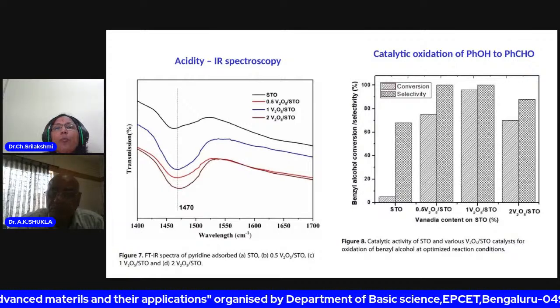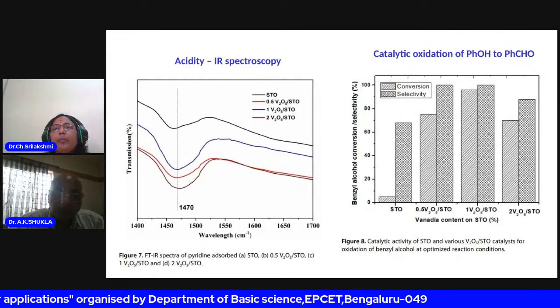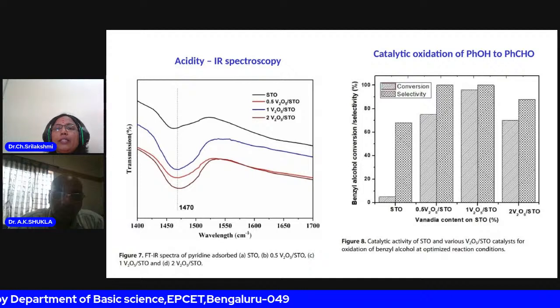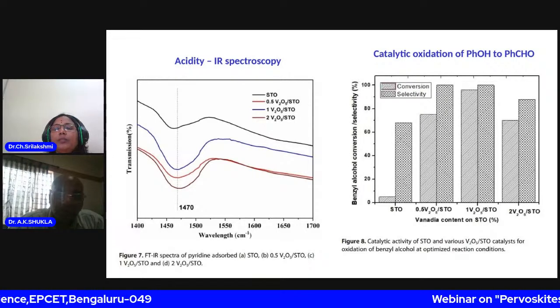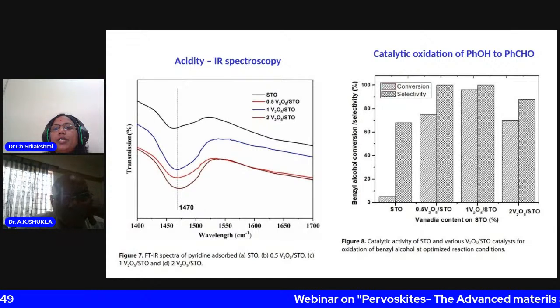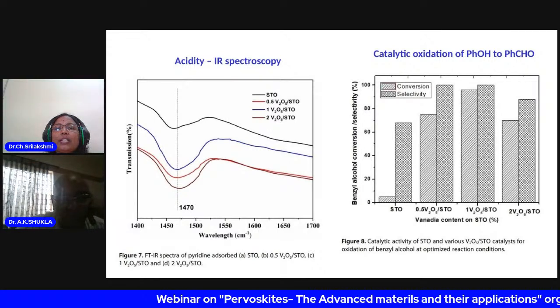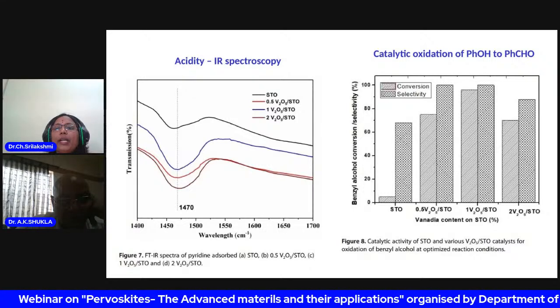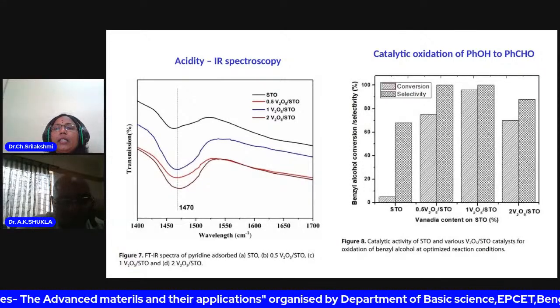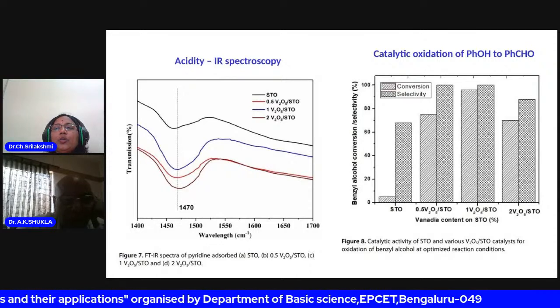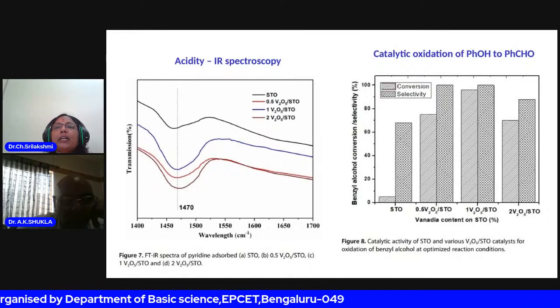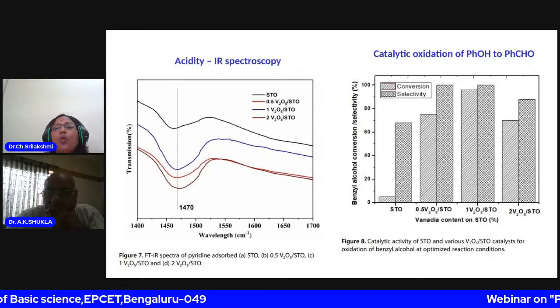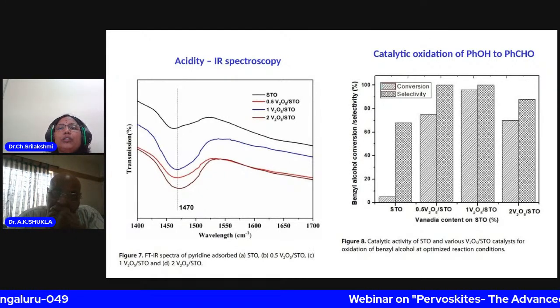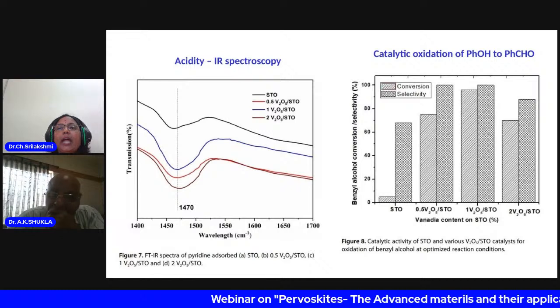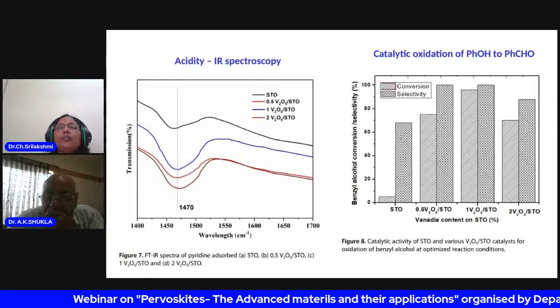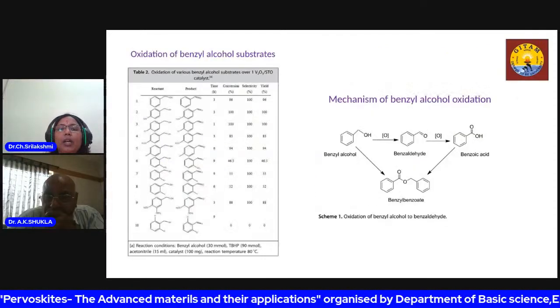So we have applied this catalyst for the catalytic oxidation of benzyl alcohol to benzaldehyde. You can see here we have conversion and variation of activity with the variation in vanadium content of the samples. You can see STO is least active but moderately selective, whereas with the vanadium catalyst, the conversion as well as the selectivity improved. So the 90% conversion and 99% selectivity is achieved on 1 weight% vanadium oxide on strontium titanate, whereas it goes down to 80 and 60, because this decrease in activity is mainly due to change in morphology of the sample.